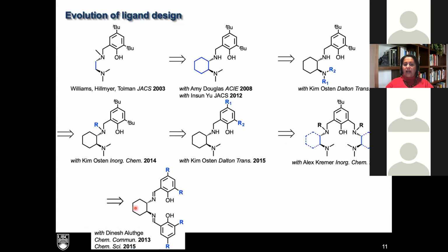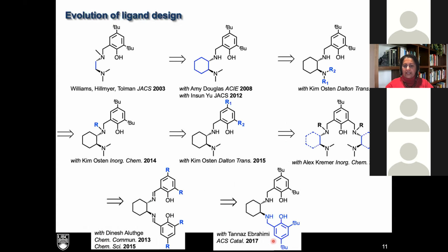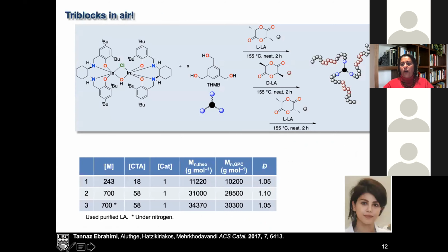We started looking at chiral systems, and so we finally ended up with this particular system that we published in 2017, which shows the culmination of this chemistry, which is basically that we have an indium compound that's an indium hydroxy with a tetradentate ligand around it. And this material is completely air stable. So it's an air stable solid that then in air we can add this alcohol to.